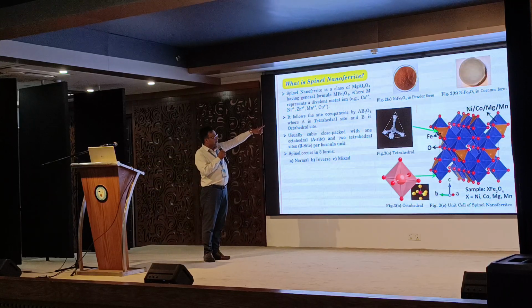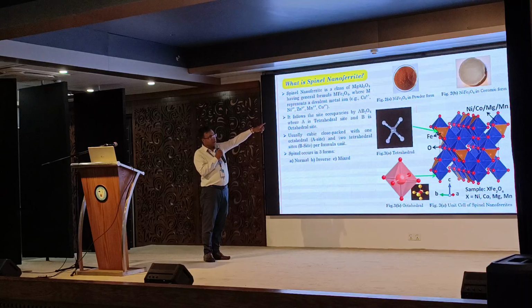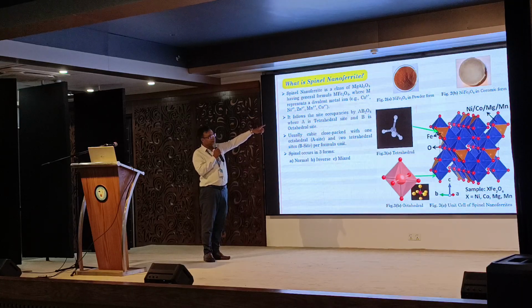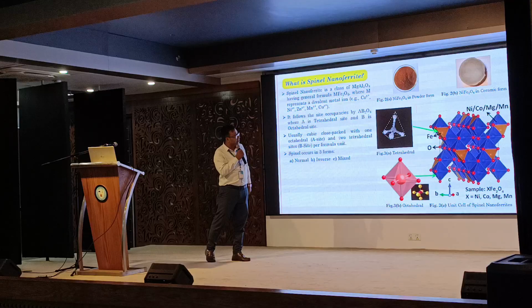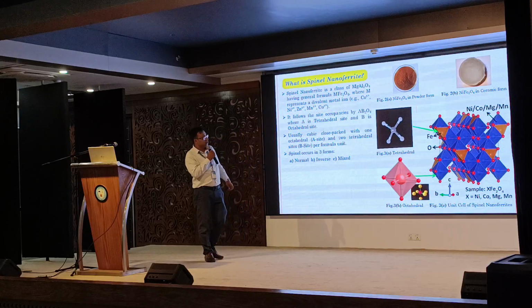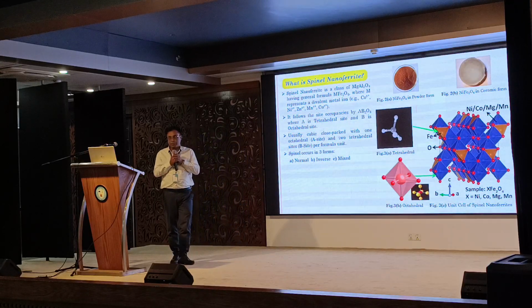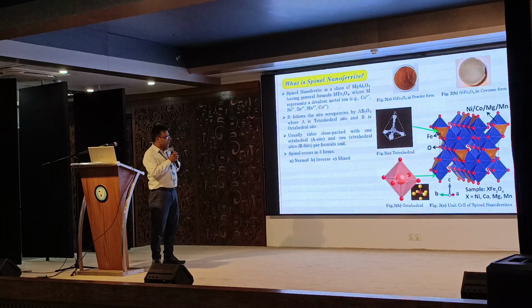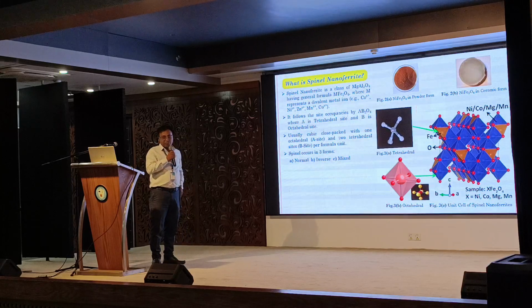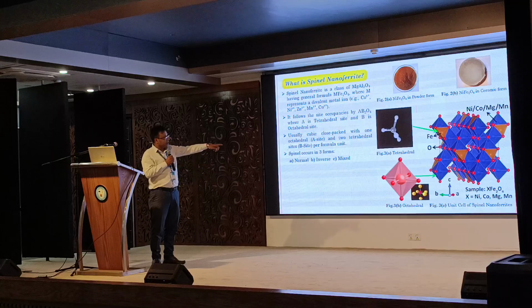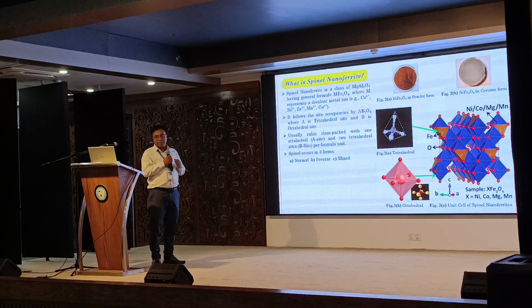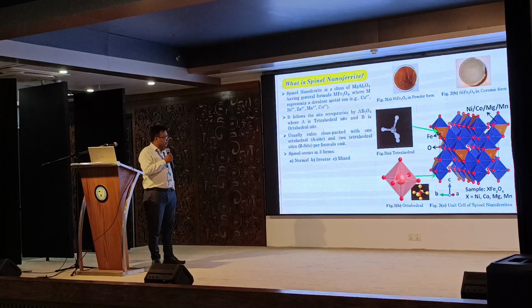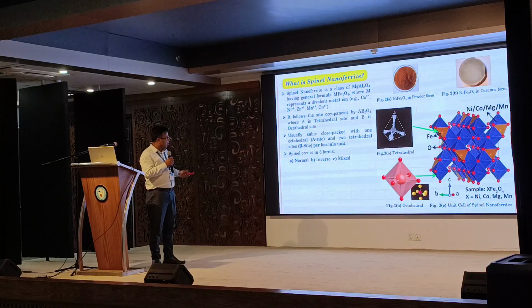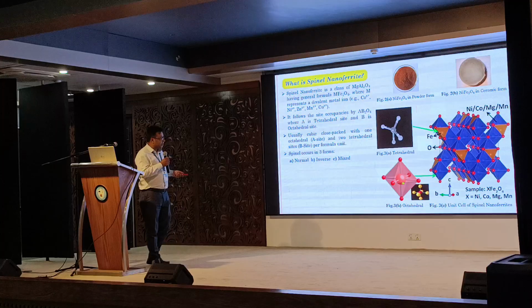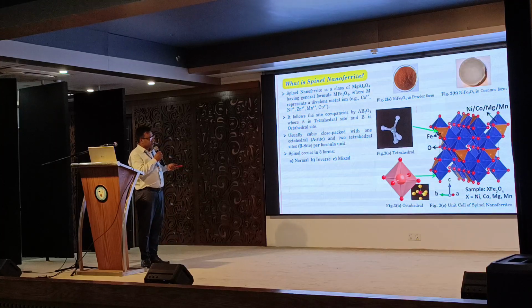So this sample is nickel ferrite, and this is the powder form that we made inside our lab, and this is the NiFe2O4 ceramic form after the heat treatment was performed. The unit cell of this nanoferrite is like this, where there are two sites. One is tetrahedral, another one is octahedral. Here is the octahedral site and here is the tetrahedral site.